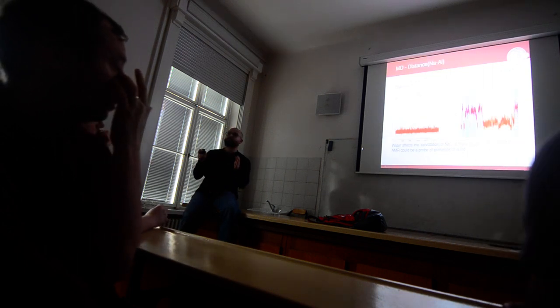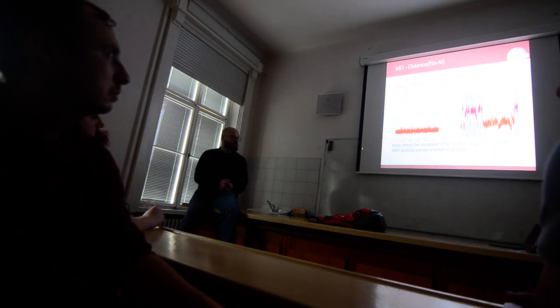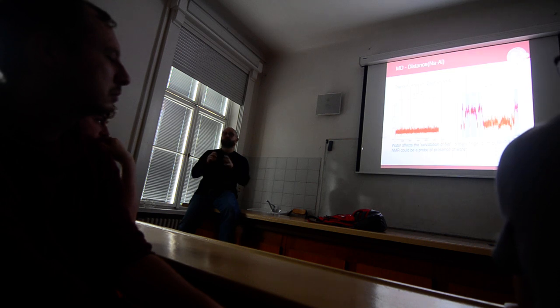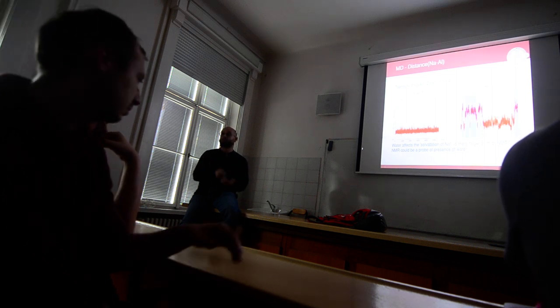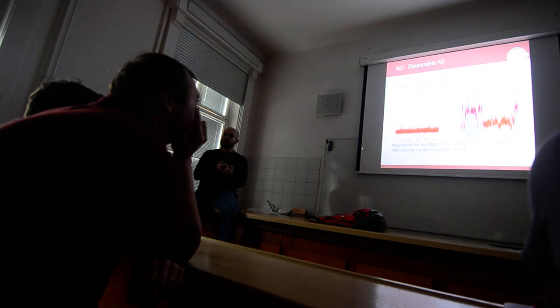In the same molecule before, we decided to keep track of the distance between sodium and aluminum. Sodium and aluminum are interacting. If you have zero water or one molecule of water, as you can expect, sodium wants to get very close to aluminum. You want to minimize charge separation. It's a bit more complex. Actually, sodium likes to sit on one of the windows of the chabazite network. You want to interact a bit with the oxygen of the frame and also with aluminum. This is very important because if you're looking in terms of the activity of the aluminum site, knowing where the counter-cation sits could be very important. But it's also important because usually you don't have perfect vacuum. You have other things in your system.